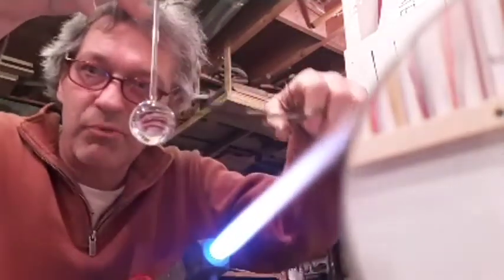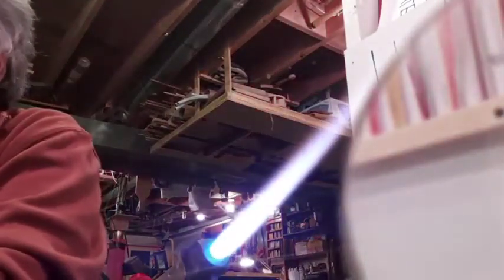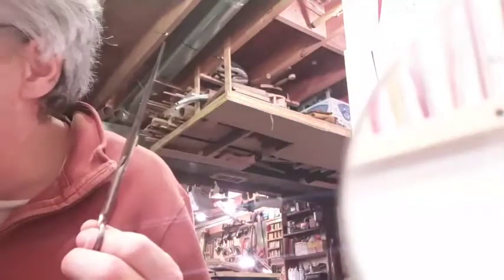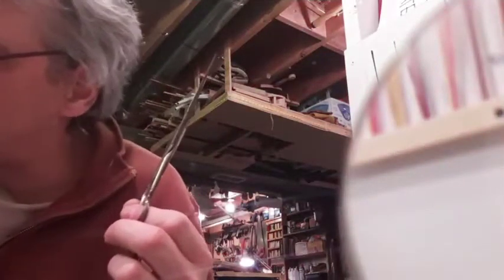Now, I'm going to use that plate with dimples in it that I showed you at the beginning. I'm going to chill this glass connection point. I'm going to tap this rod. It's going to detach right where I chilled it. So here, I'm just going to make a cutting motion with my jacks. The rod popped right off. I'm going to pick up my torch and polish that last attachment point. I want any little bump that last glass rod left to pull smoothly into the surface.